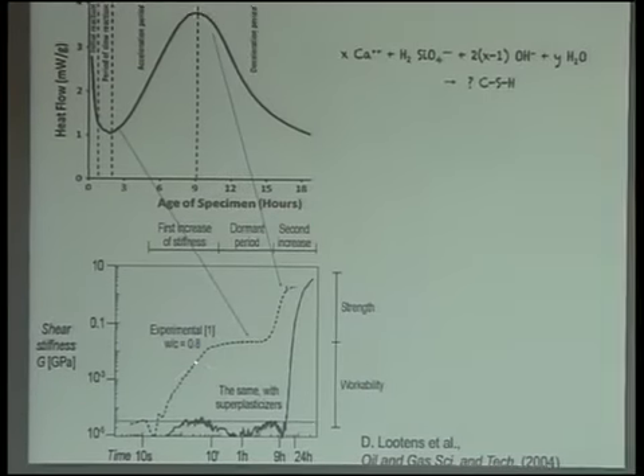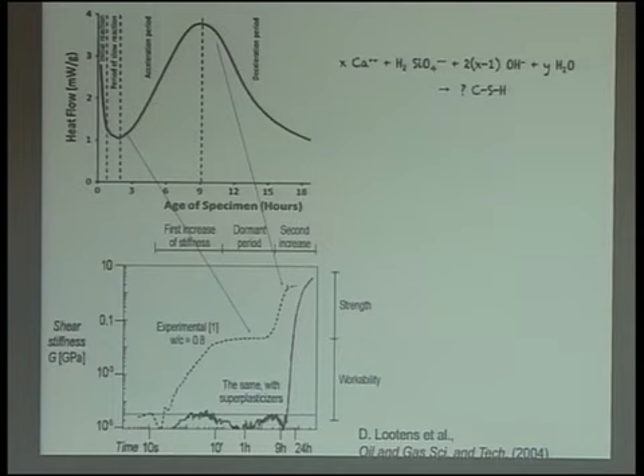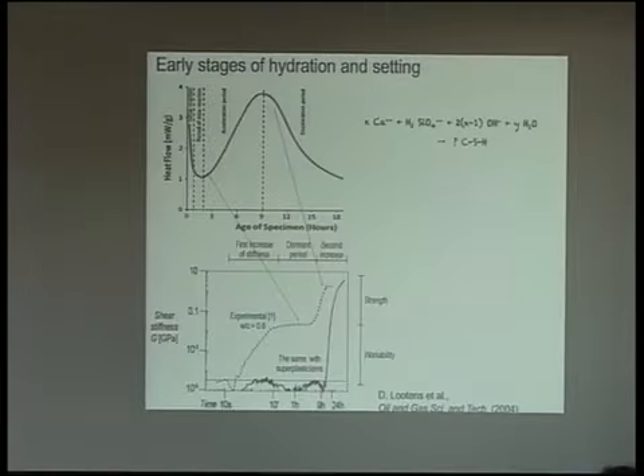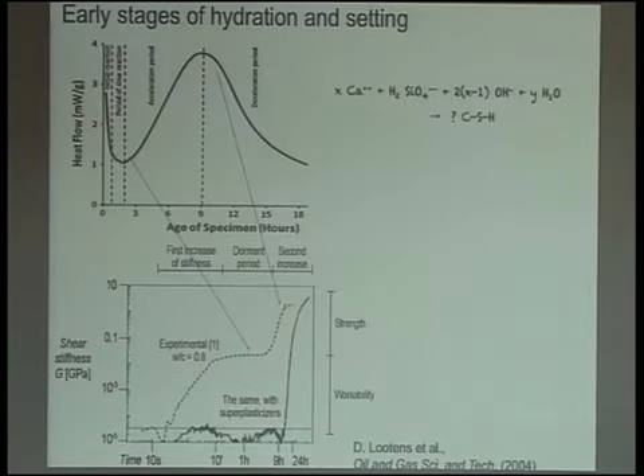This is the development of the mechanical properties. So you can see that there is an evolution of the strength of the material that is actually coupled to the different steps of this kinetics. So the physical properties of the material are coupled indeed to the different steps of this kinetics, and so it's clear that the problem is more complicated than what you would think, and you need to understand this interplay between the evolution of the chemistry and the evolution of the physical properties. From such an intimate interplay between the physical and the chemical properties of the system, I think that is suggestive of what happens in some biological systems when the two things are so intimately related.